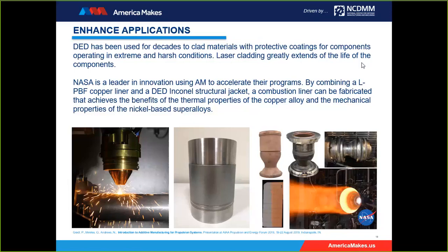NASA takes the AM technology one step further by combining the two AM technologies described earlier. The laser powder bed fusion copper liners exhibit intricate cooling schemes to allow for higher firing temperatures. The parts are then cladded in an Inconel structural jacket to increase the mechanical strength of the final component. It is truly an application where the advantages of both technologies are used to make parts that were previously impossible or would have incredibly long lead times.